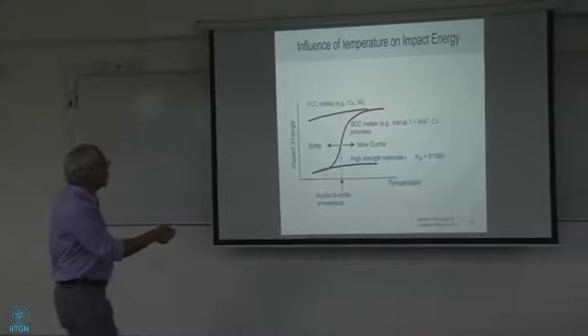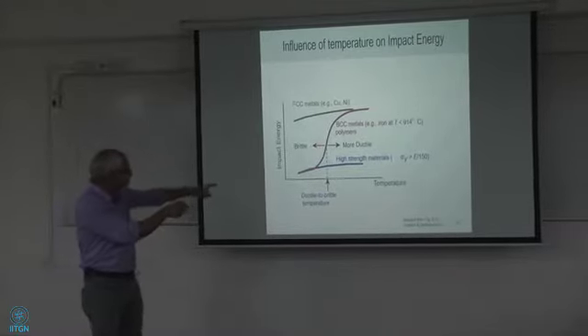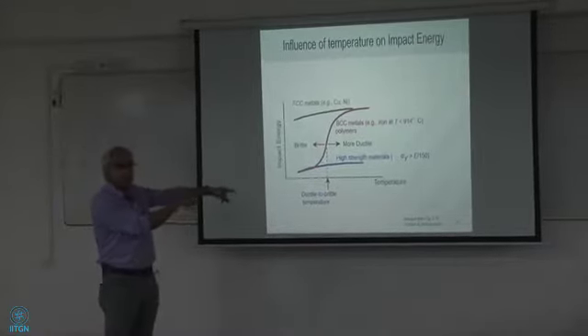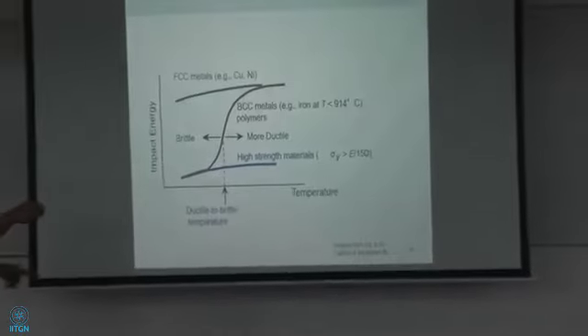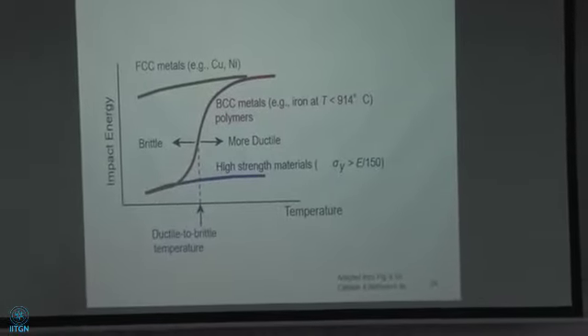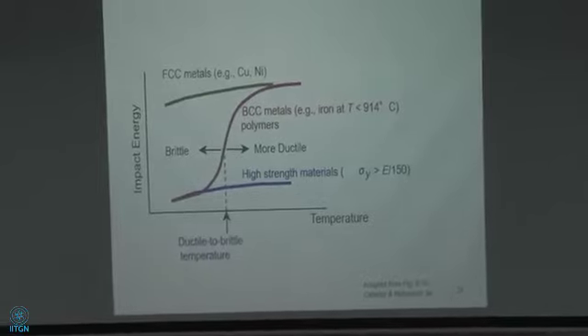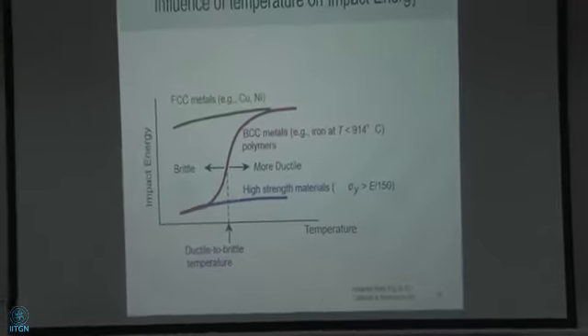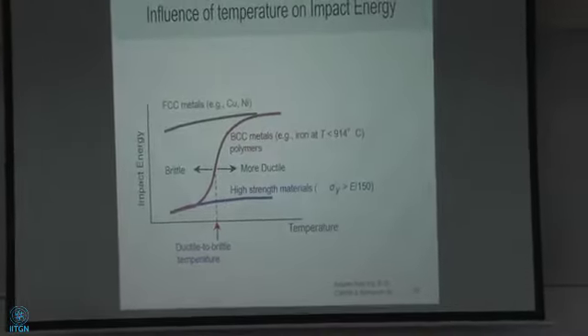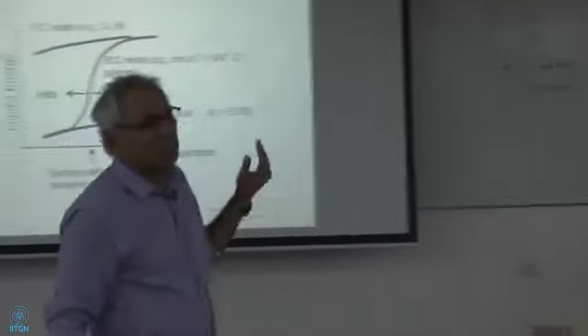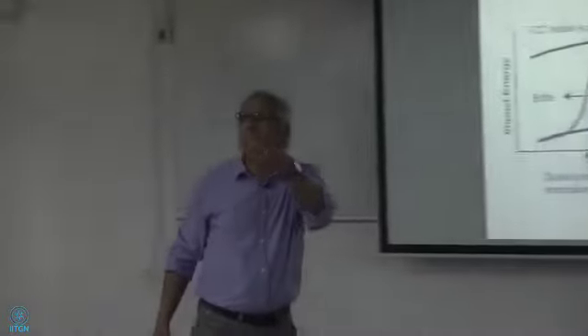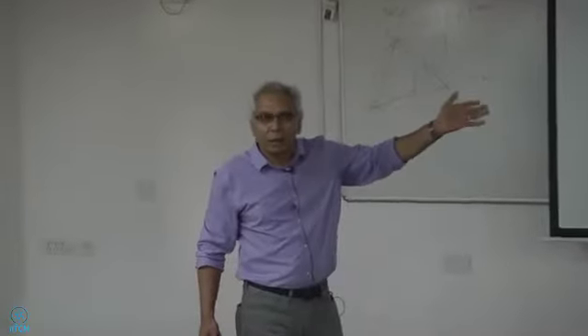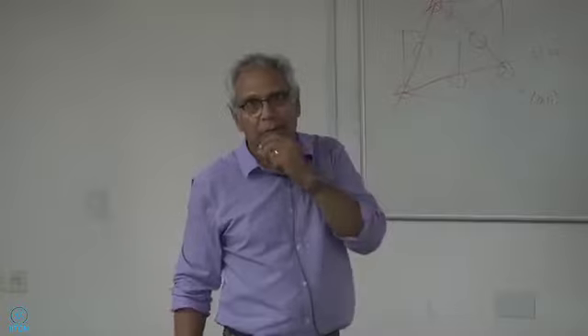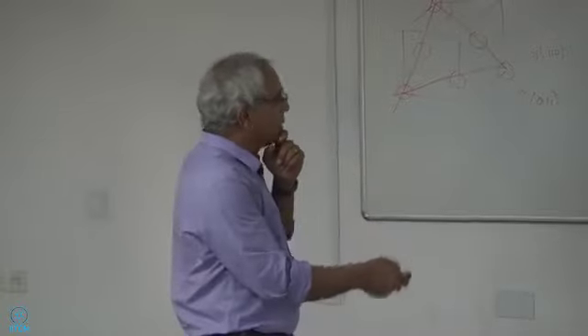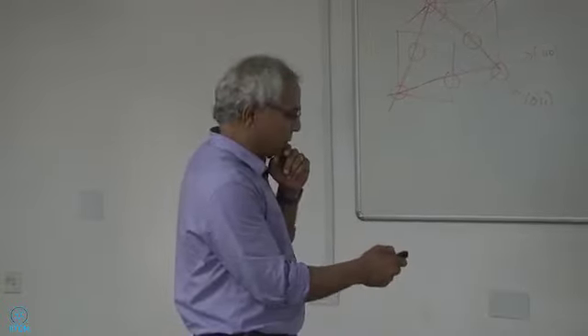Okay, so you get this inflection point. That is your ductile to brittle transition temperature. That means above this temperature, the material acts ductile, and below this it turns brittle. It's very important, actually, and it's very cheap to do. Machining the samples is not that expensive. You can get a very quick ductile to brittle transition temperature. And the reason I like this is because, well, I don't have a picture of it.